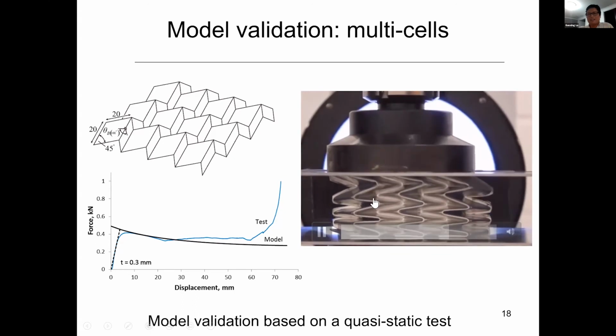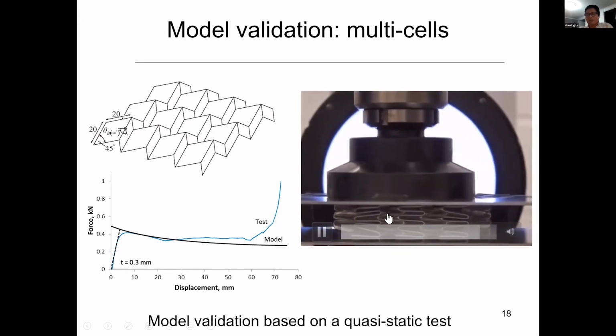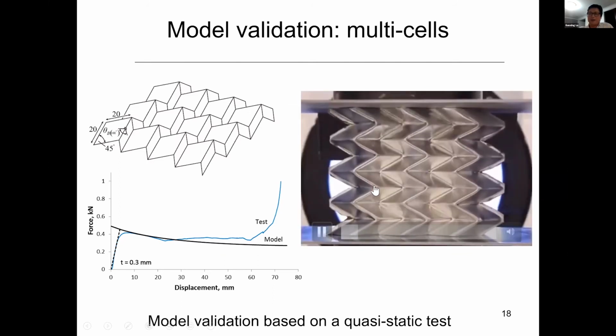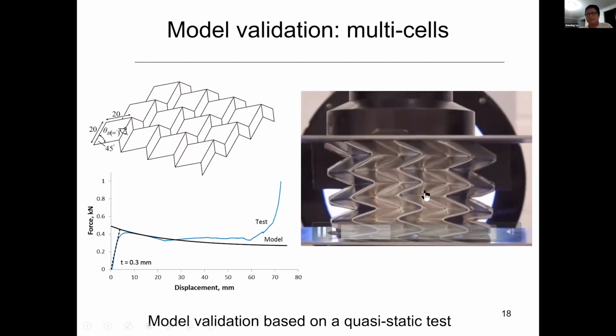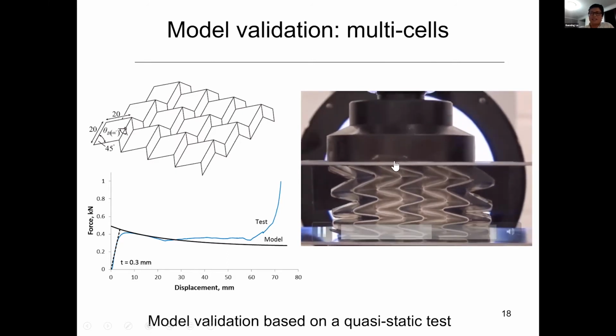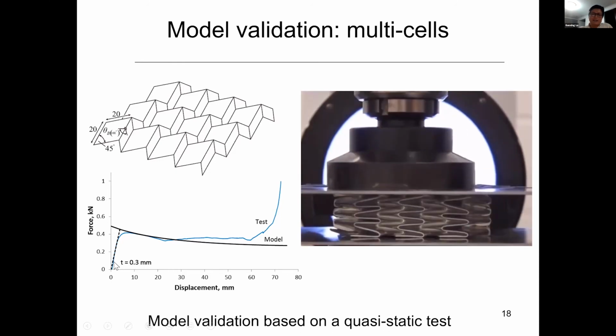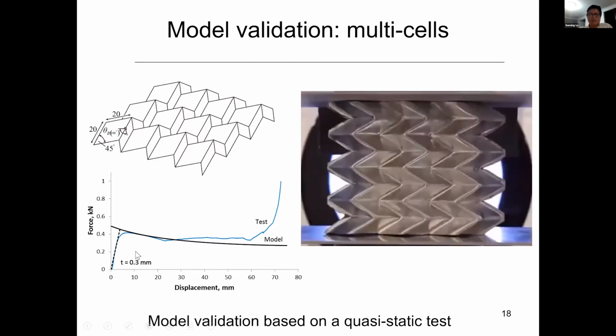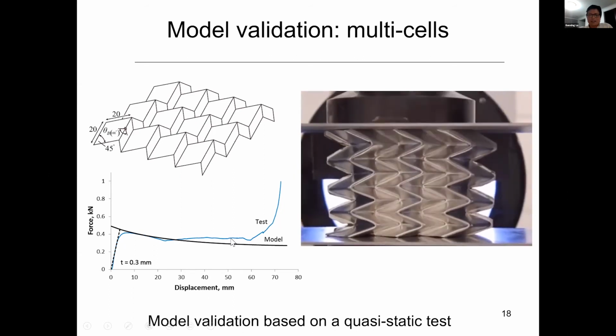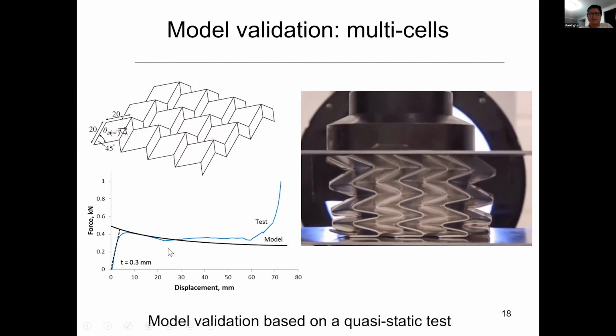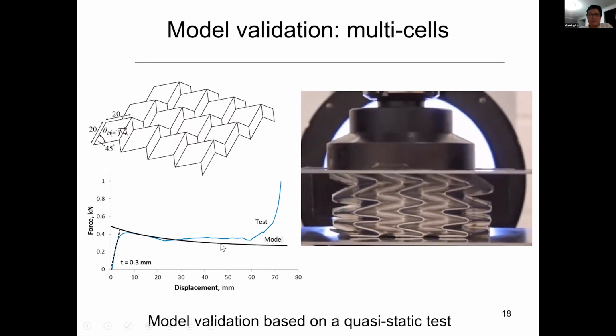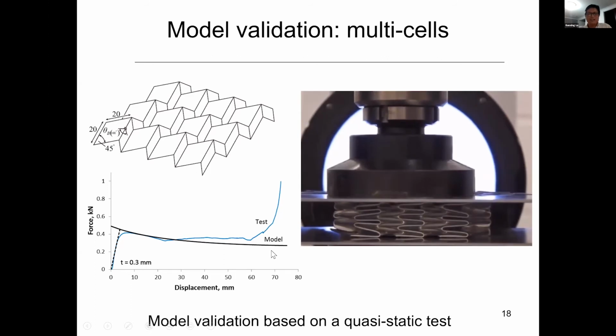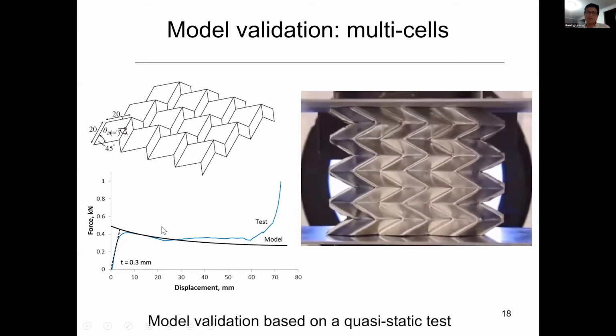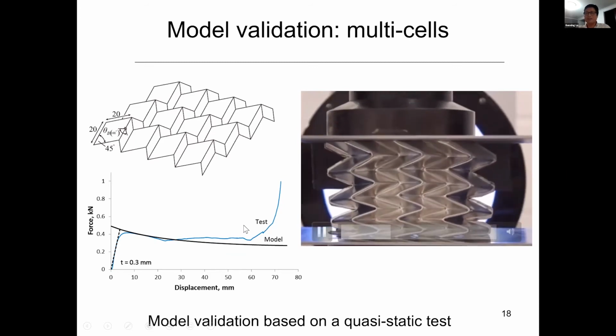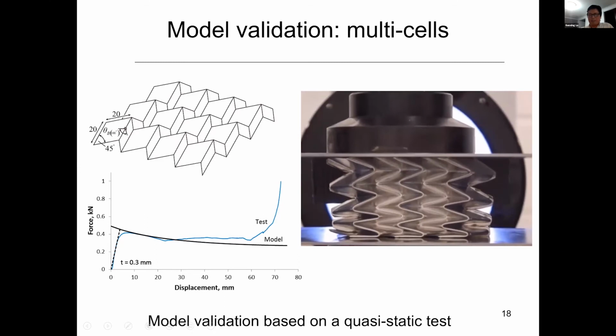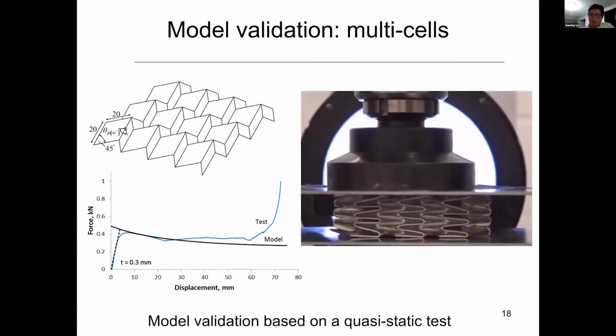On the right-hand side, we actually made this piece of material. We had 4 layers of these origami sheets and then glued them together. It's made of aluminum, and then we do a quasi-static compression test. On the left-hand side, we have a force displacement curve. The solid line in blue is the test results, and the solid line in black is the analytical result. Again, our very simple analytical result agrees fairly well with the test result, even though we have made the assumption of a rigid, perfectly plastic model.